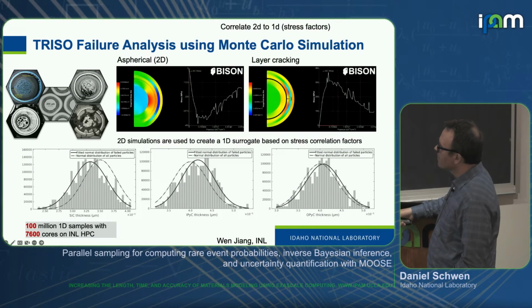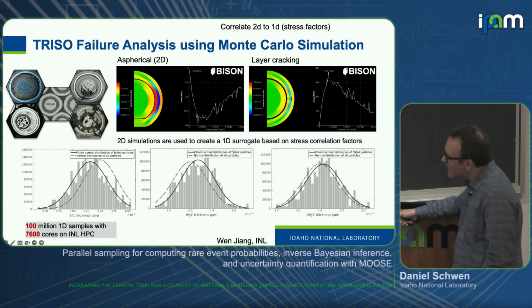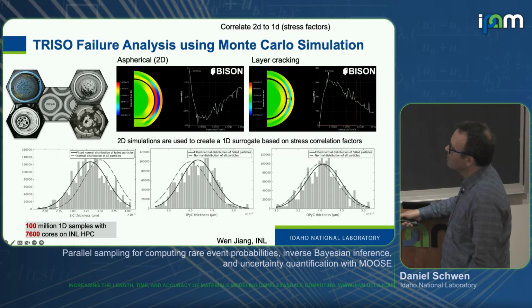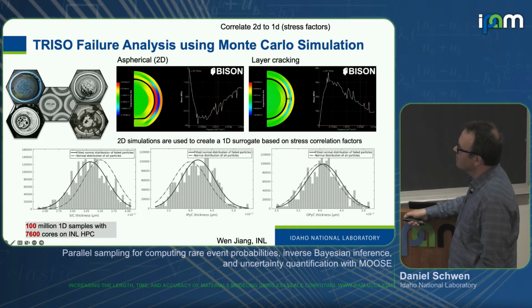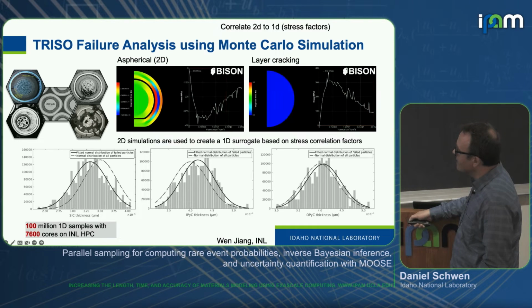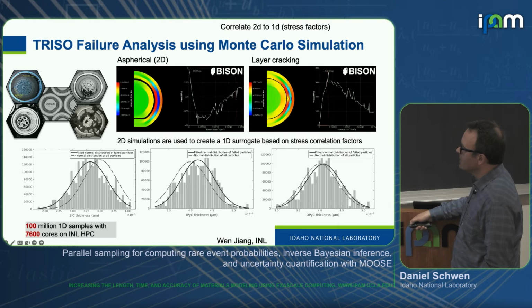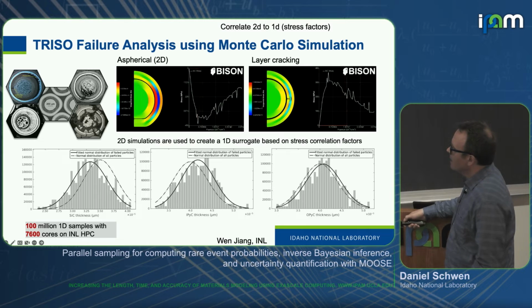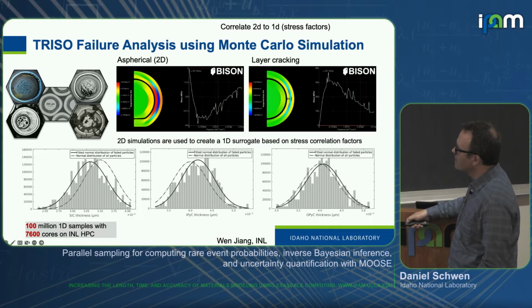So he did 2D simulations of aspherical particles to see how the asphericity drops the failure threshold, and then did 100 million 1D samples on 7,600 cores on INL HPC. It took a day or two. And you get a distribution of failing particles, and you can plot this distribution with respect to the particle parameters like silicon carbide thickness, pyrolytic carbon thickness, outer pyrolytic carbon thickness.